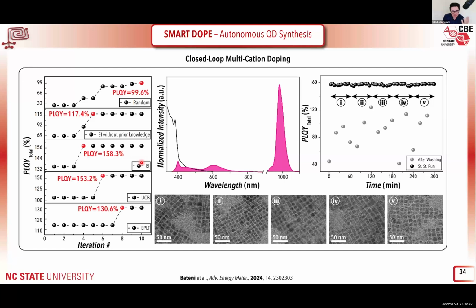And in this case, we showed that we can autonomously discover the best-in-class cation-doped perovskite quantum dots within only 1 day that improves the total quantum yield of this specific class of quantum dots by 25% versus the best number reported in the literature.